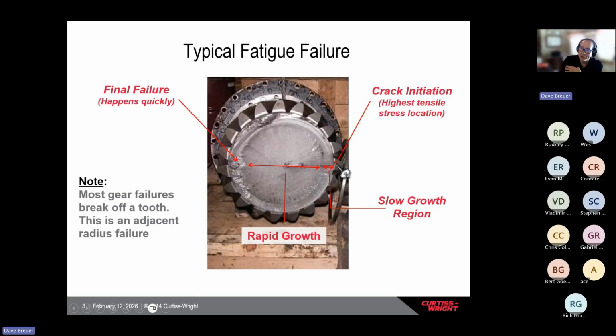When the crack is very shallow, it grows slowly. As the crack grows into the surface, it grows slowly while shallow, and then once it gets to a certain depth, it starts to grow more rapidly. Let's say it took 250,000 cycles to start, 250,000 cycles to grow this deep, and as the crack grows faster, let's say 250,000 cycles to traverse across the cross section until there was so little left, it just ripped off the remaining portion.